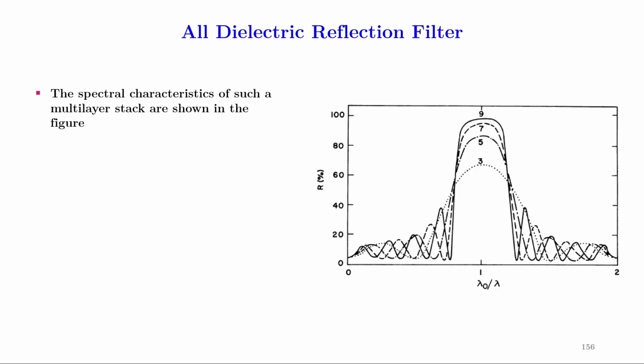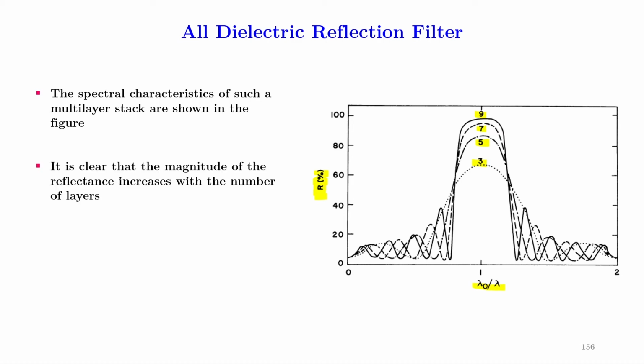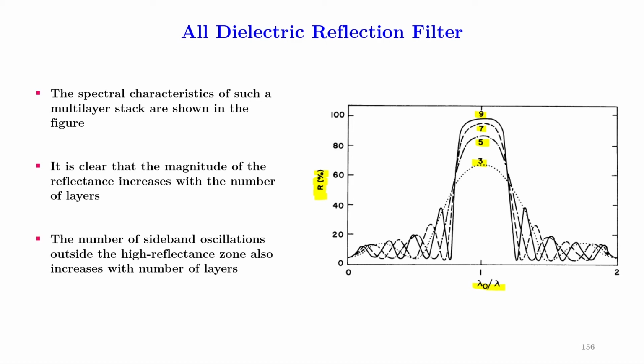This figure shows the spectral characteristics of such a multi-layer stack. On the x-axis we have plotted lambda 0 divided by lambda, and on the y-axis the reflectance in percentage. In this figure, 3, 5, 7 and 9 indicate the number of layers of the thin film on a substrate. It is clear that the magnitude of the reflectance increases with the number of layers. The number of sideband oscillations outside the high reflectance zone also increases with the number of layers.